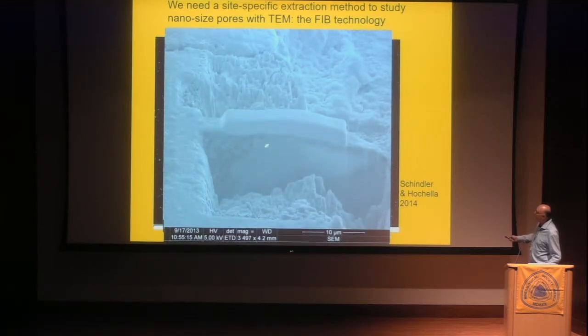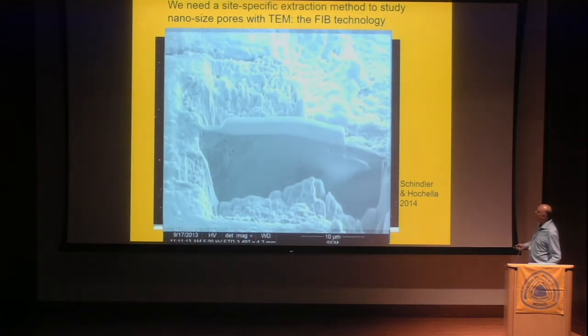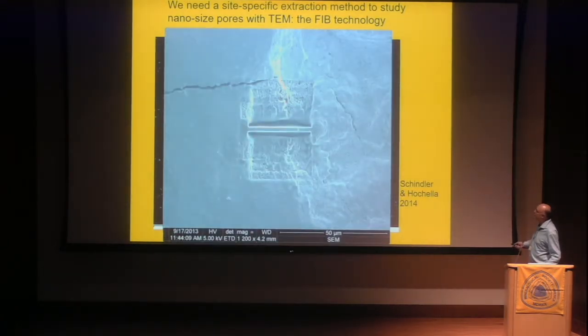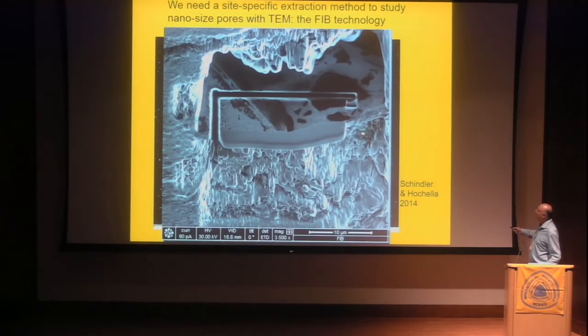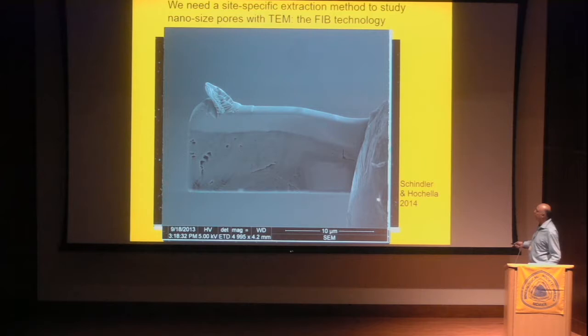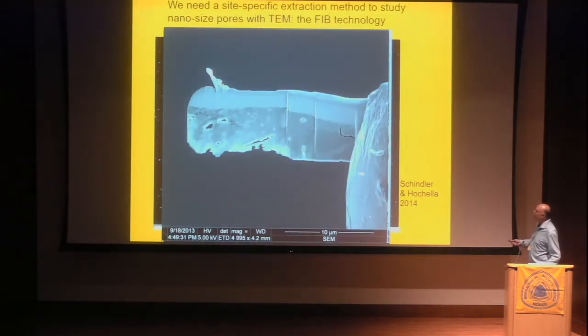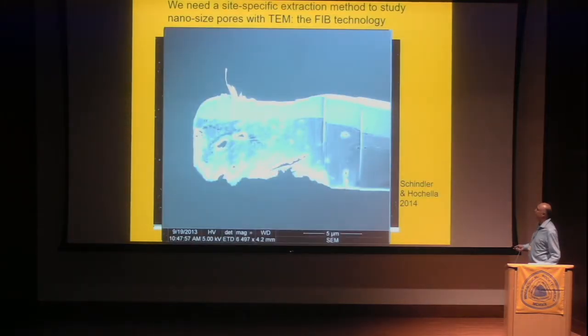You continue to sputter until you already see here's the area of interest, here's the interface you want to look at, and you continue doing this, and then at the end you flip your sample around, you cut it off, and you mount it on a sample holder, and then with the gallium ions again, you are creating an electron transparent section for transmission electron microscopy.